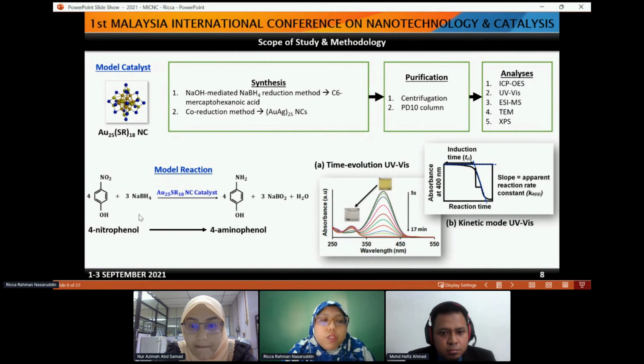So this is just nitrophenol hydrogenation in solution, where you can have time evolution UV-Vis in order to see how long it will take for the reaction to complete. And also you can find the induction time for the accessibility and also the apparent reaction rate constant by using this kinetic mode of UV-Vis analysis.